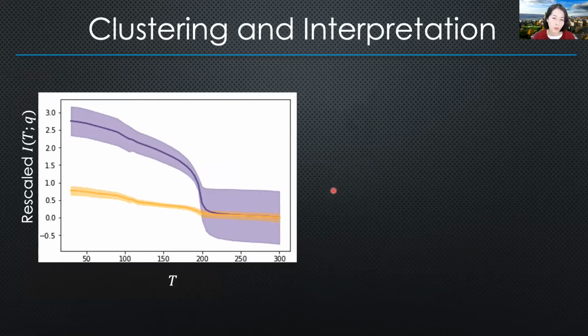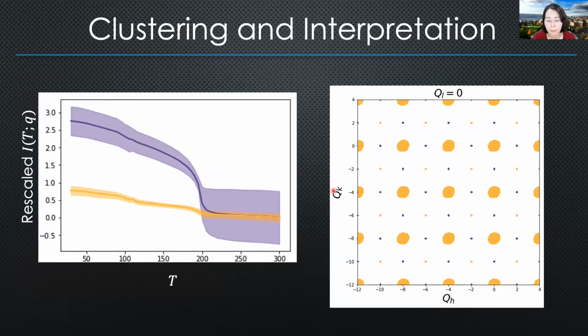This is what we get when we assume 2 clusters. And what you're seeing is the clustering mean and variance. It says that there are some Q points that seem to be best captured by this kind of behavior as a function of temperature, the intensity rising, suddenly starting to jump up around 200 Kelvin. And then there's another cluster that is showing a much gentler dependence.